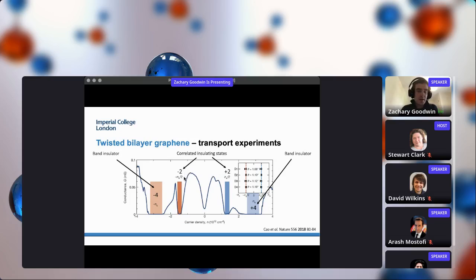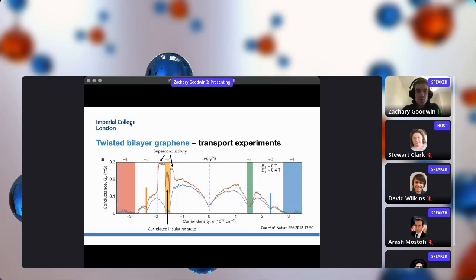So this is where you would expect to find the Van Hove singularities in the non-interacting electronic band structure, which would have a high density of states and a high conductance. But in their experiments, at low temperatures, they found these correlated insulating states. And this generated quite a lot of interest. But moreover, subsequent experiments performed by them found superconductivity in proximity to these correlated insulating states. And this generated really quite a lot of excitement in the field of two-dimensional materials and strong correlations.